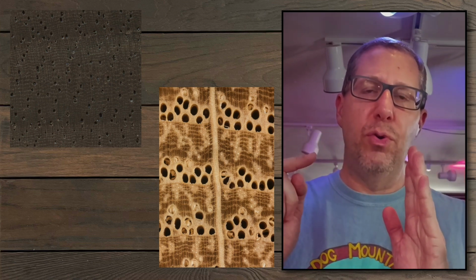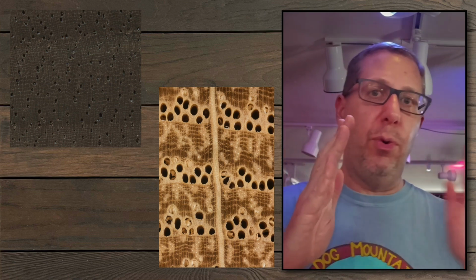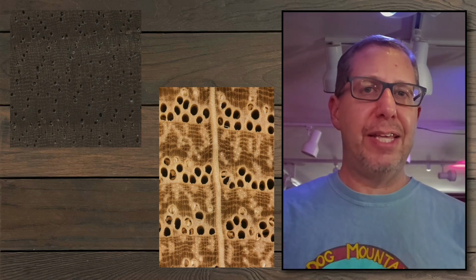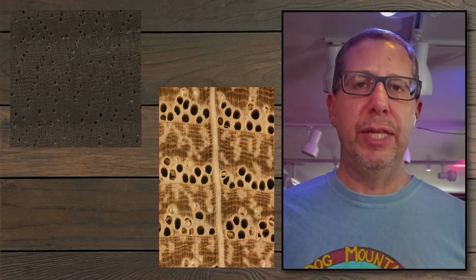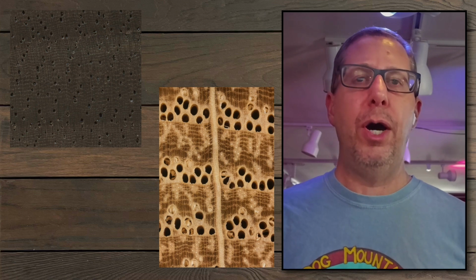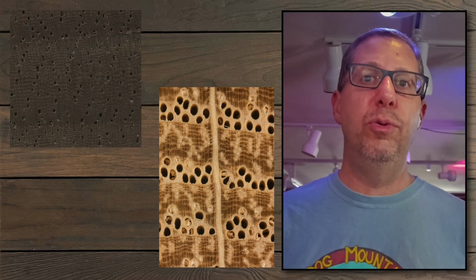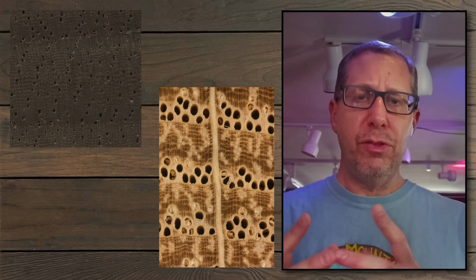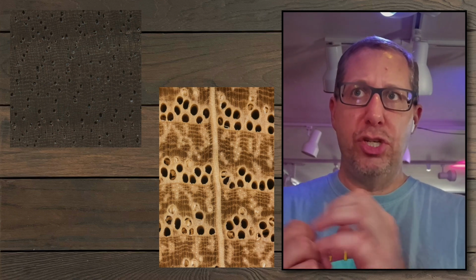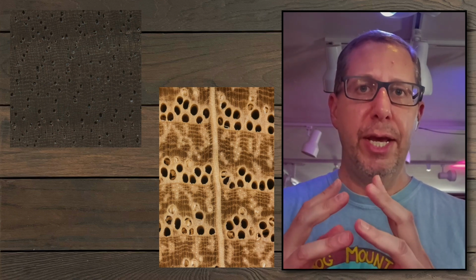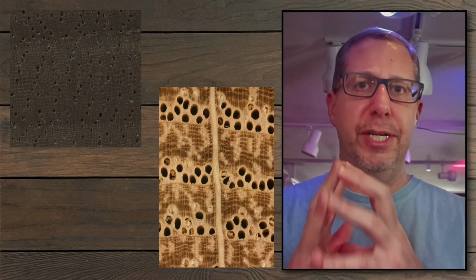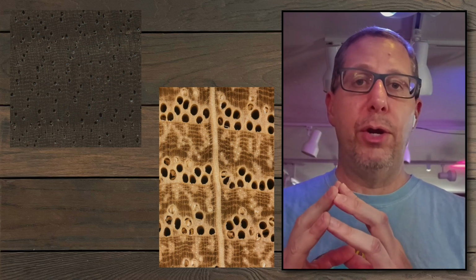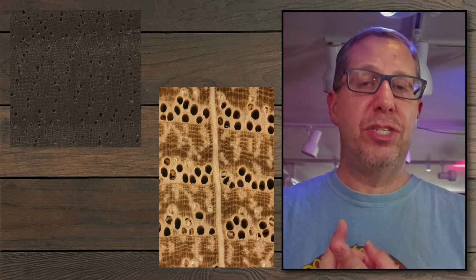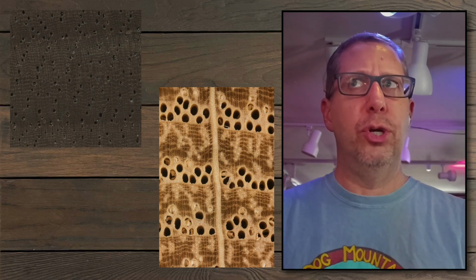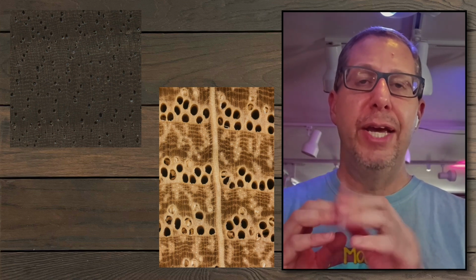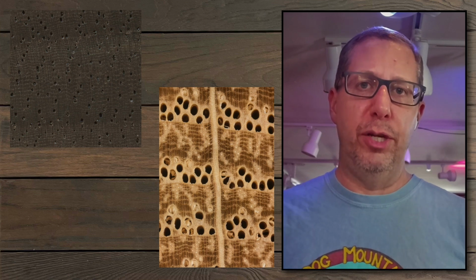That moisture has got to move from the middle of the board. It's got to move 4 feet to get all the way near the end. There's a lot of surface tension in there. It can be very difficult to move all that water. And that free water that's just in those pores, in those tubes, it's going to cling through adhesion to the cell walls, but also cohesion. The water molecules themselves are going to stick to the other water molecules, and it can require quite a bit of force or quite a bit of heat, some external factor, I should say, to drive that moisture even to the path of least resistance longitudinally.